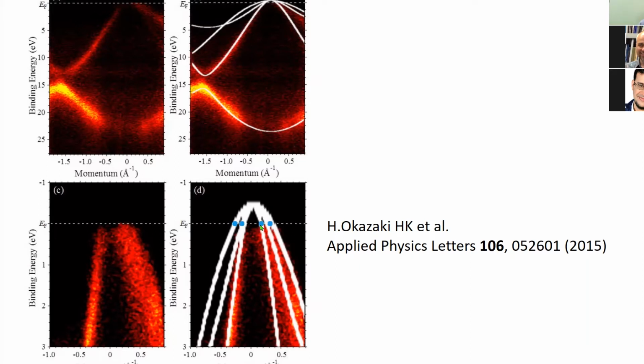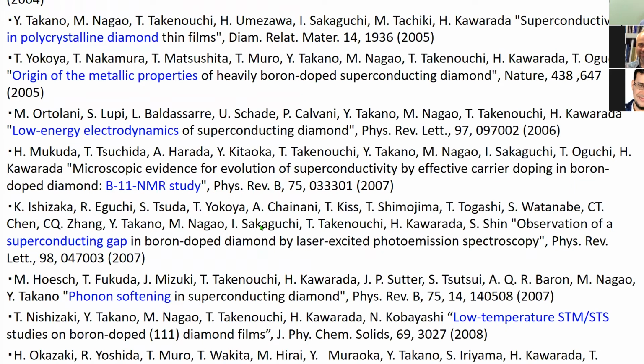So, in the early stage of superconducting diamond, we started from 2004, and after the first paper was published from Russia, we started using CVD. We made some contributions to CVD and polycrystalline diamond, getting relatively high TC. Then gradually we learned how to make these layers, and many basic research people measured our samples, and we're going to show you some of those results.